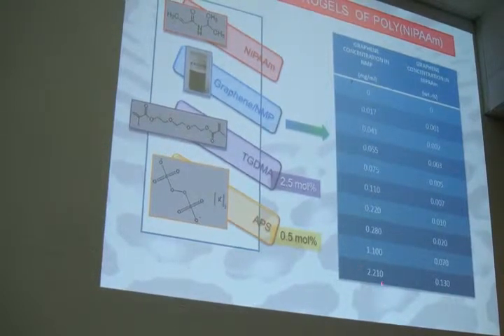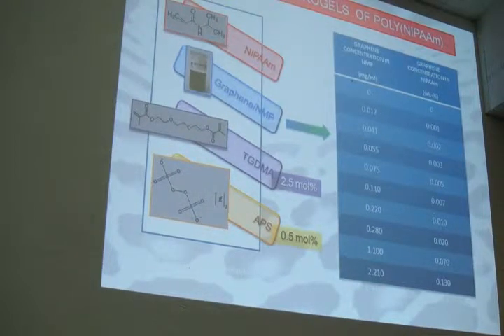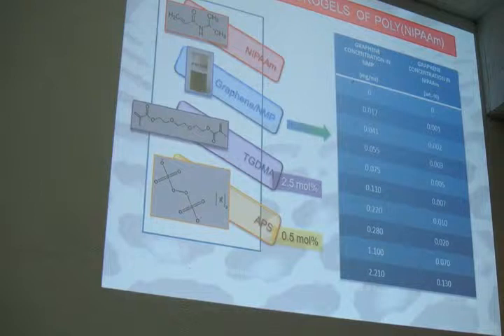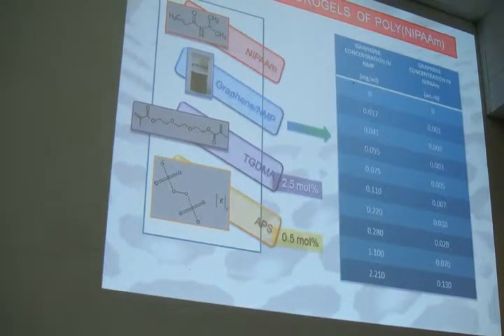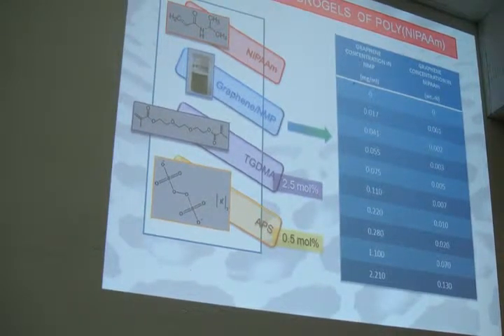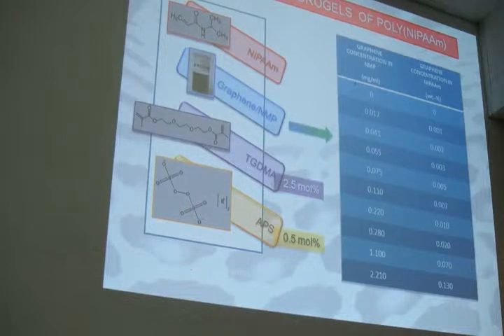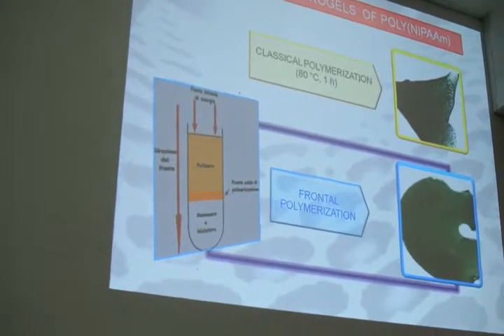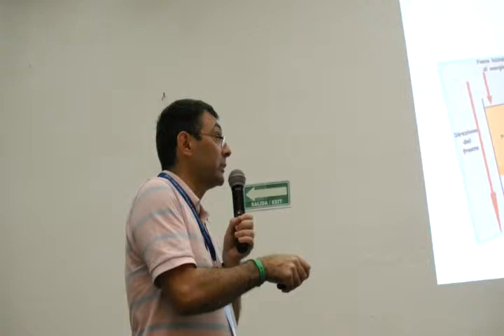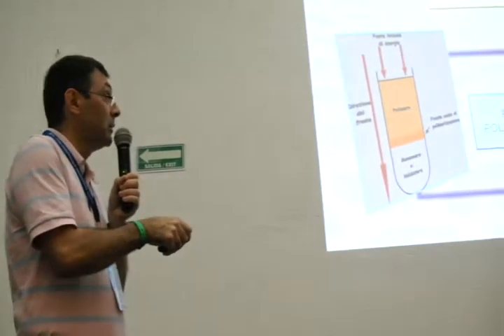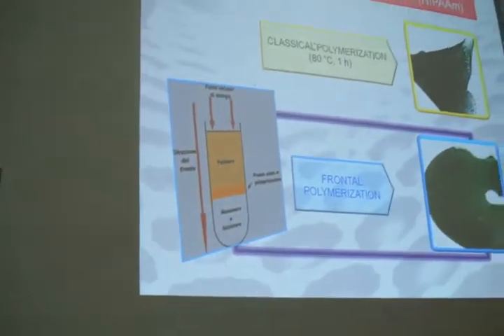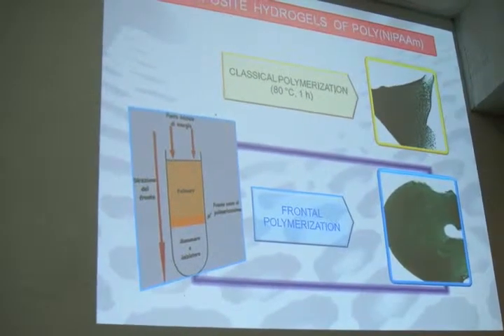We prepared a master batch dispersion in N-methylpyrrolidone, and then we added the monomer. So we have a solution containing monomer, graphene, and methylpyrrolidone, and we diluted it, so we obtained these different dispersions. Then we polymerized it, first by using the classical polymerization. This means 80 degrees for 1 hour, but what we obtained is reported here. You can see that all of them are aggregates. It means that during the polymerization process, you have the reaggregation of graphene to graphite.